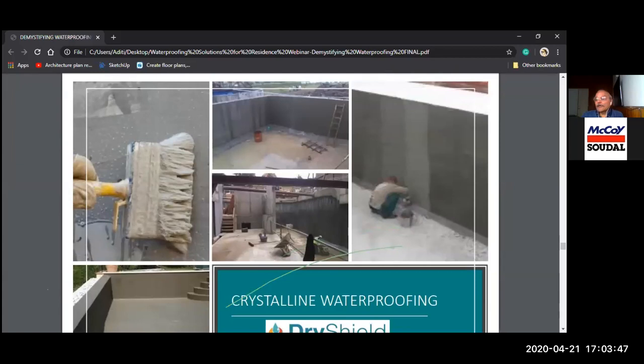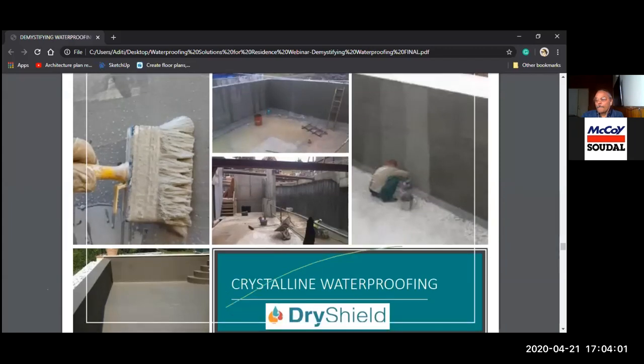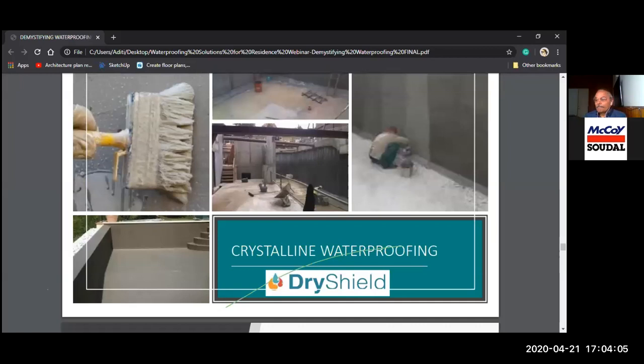These are some of the images of crystalline coatings. See, crystalline coatings are very versatile, and it creates a barrier and diffuses itself into the concrete and blocks water from all the pores. So this works well with all masonry and concrete, and performs very well against negative side pressure. And as I said earlier, it's a versatile system and works on the hydration process, and is very easy to mix at sites. It's not difficult at all.